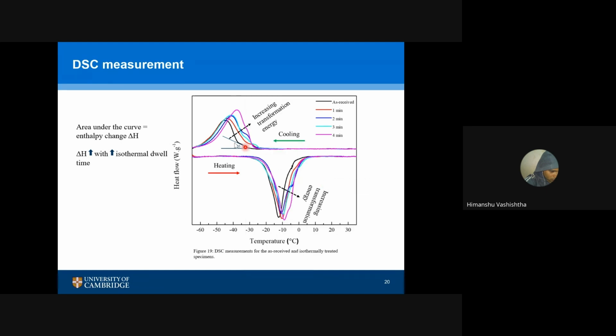Let me highlight it. So here you can see it, roughly minus 25 degrees. When I'm heating it at 1 minute, 2 minutes, 3 minutes, 4 minutes, this abrupt thing is going away. So we are saying this abrupt feature was there because of the dislocations, and when we heat it, it goes away.